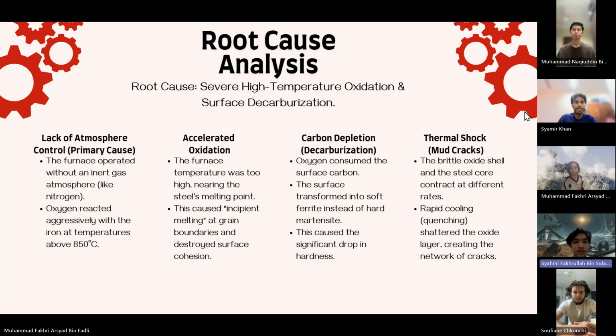Then the second one is accelerated oxidation. The furnace temperature was too high, nearing the steel's melting point. This caused incipient melting at grain boundaries and destroyed the surface cohesion. Next is the carbon depletion or decarburization. So the oxygen consumed the carbon at the surface. The surface transformed into soft ferrite instead of hard martensite. This caused the significant drop in hardness.